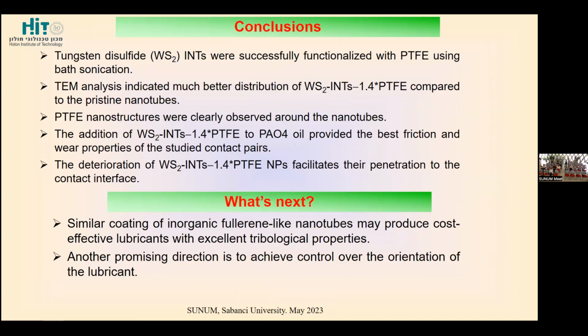Now I will conclude this part of my talk. We successfully functionalized the WS2 nanotubes with a Teflon coating using bath sonication. TEM analysis indicated much better distribution of these nanoparticles compared to pristine nanotubes. Teflon nanostructures were clearly observed, and the friction coefficient decreased. Deterioration of Teflon coated nanotubes is quite low, but if it takes place, it even facilitates penetration to the contact interface and contributes even more to the friction. There is still a lot of work to do to improve and study this process, but we have already published this work, and some industrial partners are quite interested in involving the process in their products.